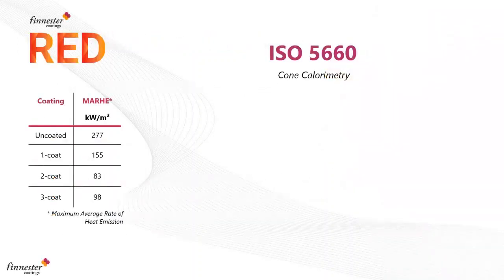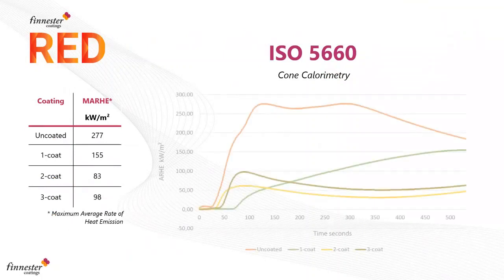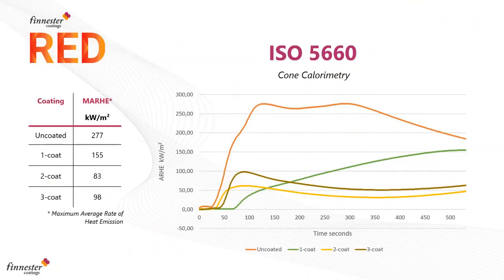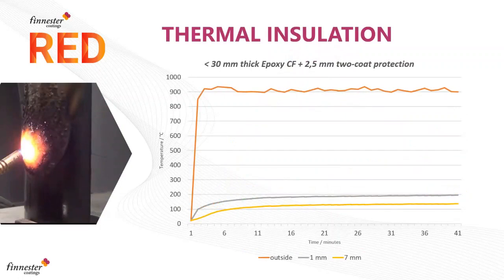These are the figures and the reporting that we can get from our cone calorimeter. So you can get the curves and you get the numbers, and we can talk them through together. What it means to have a MARHE of 98 in a 3-coat system, but actually lower MARHE in a 2-coat system. And then we have an example here that we have a thermal insulation test.